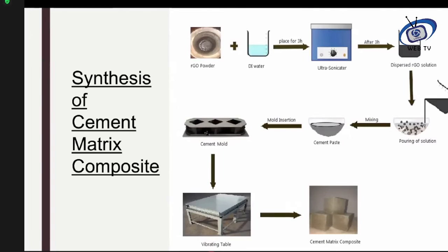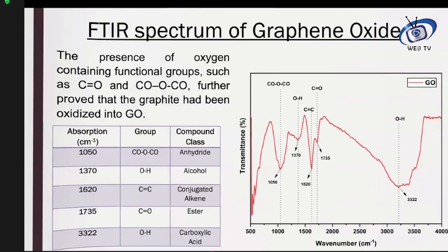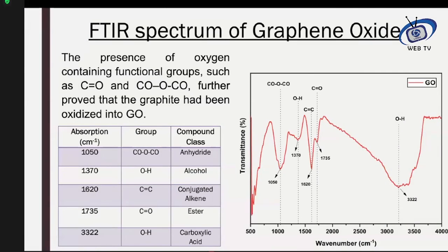One of the cement blocks, called the controlled block, was without the inclusion of the nano reinforcement of reduced graphene oxide, and the others were with 3 ratios of the RGOs. The characterization techniques used for the inclusion of the nano reinforcement into this cement were FTIR, XRD, SEM, and then some testing with a UTM was done.